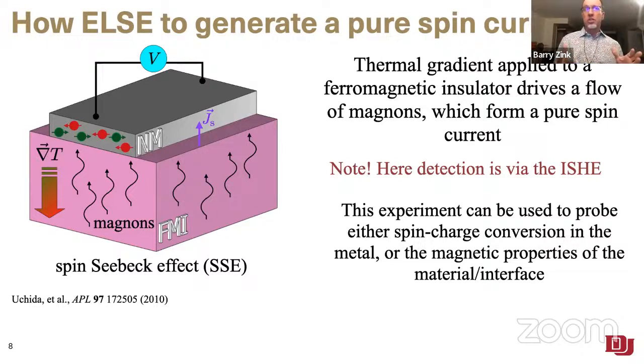So in this particular case now, we've taken a ferromagnetic insulator, that's this pink thing in the cartoon, and you apply a thermal gradient to it. Now, it's an insulator, so we can't do this thing of moving the charges around anymore, but we do have spin dynamics in the insulator, and so that means we have spin waves, or we can talk about them as magnons if we like. So when we apply a thermal gradient to a system like that, we create an incoherent flow of magnons that are driven along by this thermal gradient.